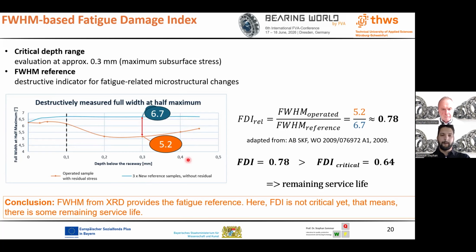The operated sample has a value of about 5.2 degrees. The new reference condition has a value of about 6.7 degrees. This gives an FDI relative of approximately 0.78. Since this value is still above the critical subsurface FDI value of 0.64, the sample is not yet at a critical state. This indicates a remaining service life margin. This means that FWHM from X-ray provides the destructive fatigue reference.